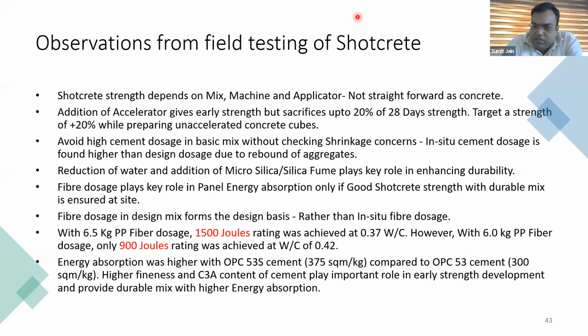Next, for the fine cement, we are using OPC 53S at our sites. 53S is a special cement which is much finer than OPC 53. And we got a very high energy absorption compared to the standard OPC 53, which was only 300 square meters per kg. And OPC 53S has a higher C3A content compared to the normal OPC. So all these factors played a very important role in early strength development, and they provide a very durable mix with high energy absorption values.